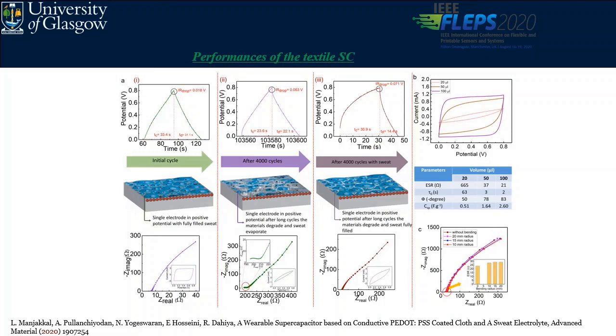Next, I carried out how the supercapacitor is influenced by different charging-discharging cycles. For example, I did the initial cycle. You can see here the charging-discharging analysis, and it shows an IR voltage drop of 0.0180, that is 18 millivolt. After 4000 cycles, you can see a single electrode at a positive potential, and then the impedance spectroscopic analysis shows almost 10 ohm resistance.